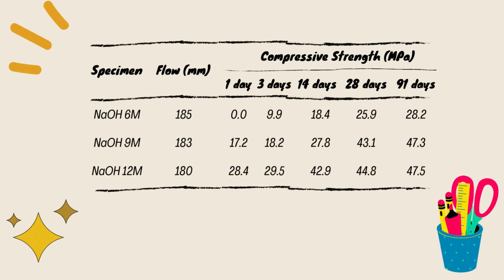Result and data analysis. For the slump test, the specimen with 6 mole molarity of sodium hydroxide had 185 mm of flow, the specimen with 9 mole molarity of sodium hydroxide had 183 mm of flow, and the third specimen with 12 mole molarity of sodium hydroxide had 180 mm of flow.